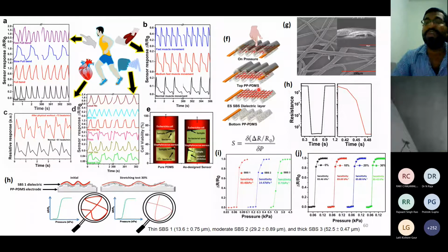Apart from that, we also do some strain insensitive pressure sensing, because we are going to use it in our body, so it will have some interference. For example, if you strain or do some workout, your conductivity will change automatically, right? So how do we avoid that kind of interference when monitoring pressure using these PPPDMS structures? We do those studies, and we checked that up to 30% strain the sensitivity is retained, which is very good performance over wearable conditions.